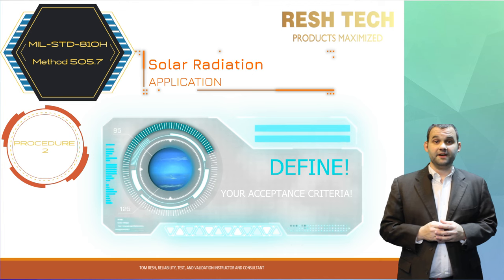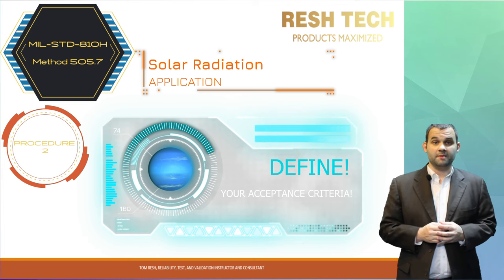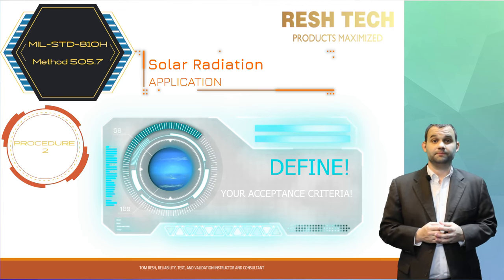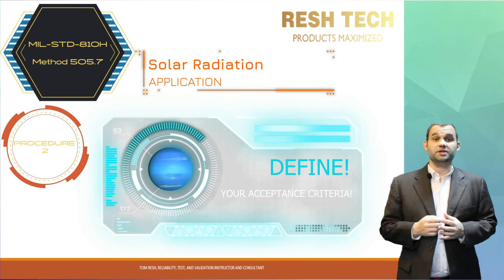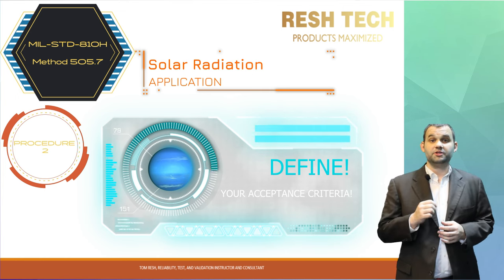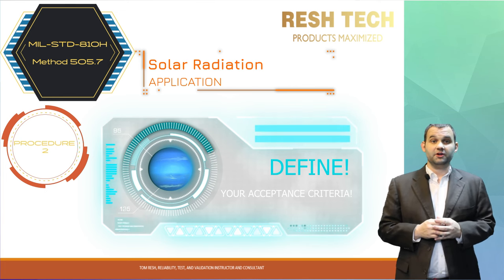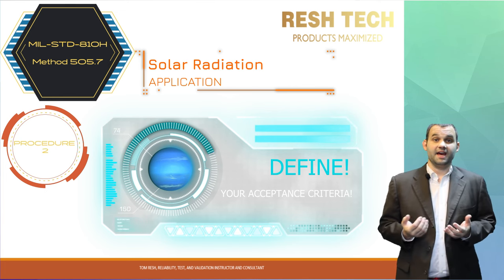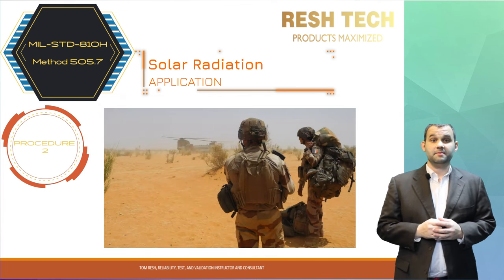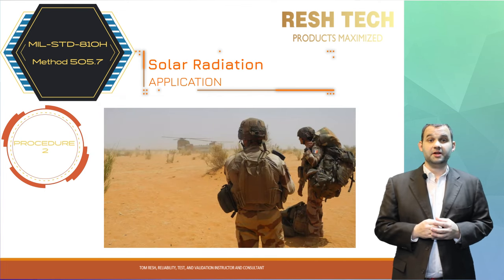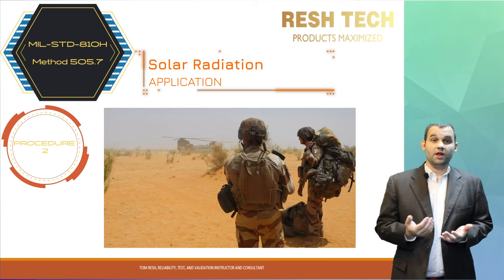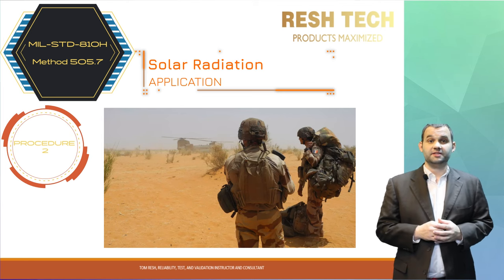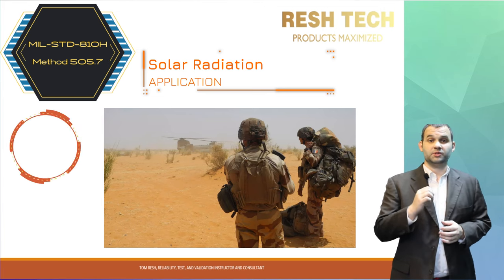Degradation due to actinic effects will be noted only as an observation and not considered a test failure. For instance, a material fading or bleaching may not be considered a failure on a particular system, while it could be a test failure on another type of system dependent on the use case and application, like a camouflage system that bleaches and gives away the location of soldiers on the ground to an observant enemy.